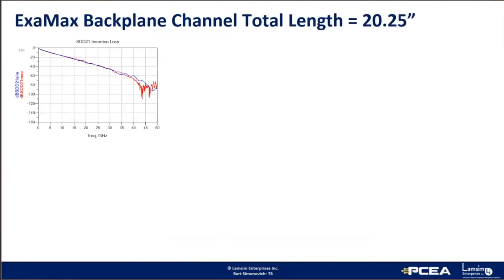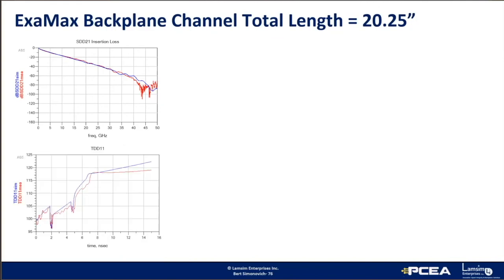After you've built the model and done your simulation, here are the results of the one channel I modeled and simulated. It's the 20.25 inch channel on the backplane. As you can see here, the red is the measured result of the channel, and the blue is the simulation. And this bottom one is the TDR plot of the whole channel of the two daughter cards in the backplane. As you can see, it's pretty good considering we're going through two daughter cards, the backplane and the connectors, and there are other impairments. So it's pretty good from just using data sheet values.